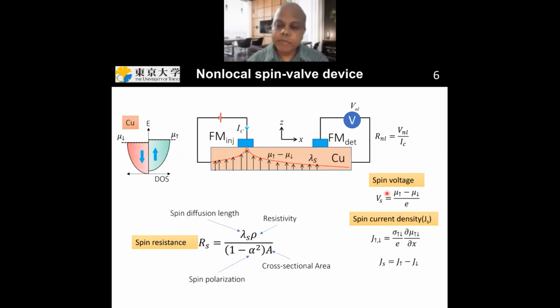You can also define a voltage, which is called spin voltage, which is the difference of this electrochemical potential divided by electronic charge. Since you have a charge and you have a current and a voltage, you can also define a resistance, which is defined like this, and which depends on the spin diffusion length and the resistivity of the metal and the spin polarization of the material and the cross-sectional area of the nanowire. In the case of copper, spin polarization is 0, so it depends only on the spin diffusion length, resistivity and area. The spin resistance is a very important quantity in spin circuits because, similar to electrical circuits, suppose you have a spin current circuit, you must know the spin resistance to calculate how much spin current is flowing in which part of the device. So I will refer to spin resistance quite often in this talk.